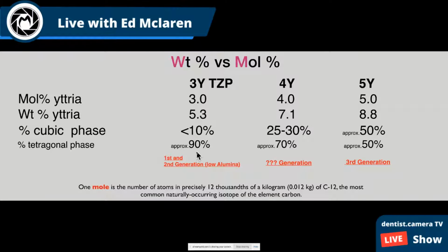What we know about the tetragonal crystals are the early materials like Lava. They're as opaque as hell. They're strong. They're 1,100 to 1,400 megapascals, and those are the materials we've been using for layering. And probably if you're going to layer a big bridge, that should be something that you consider. You're going to put a little bit of porcelain on, and like Alessandro said when we opened up, it's a little bit like white steel. So it's replacing our metal and our metal ceramics, and that's a good place to be. So this is where you should be thinking about if you're going to layer traditionally.